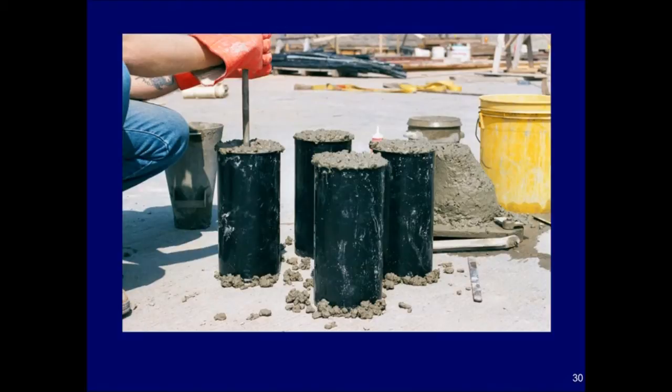Chapter 5 allows a small number of tests to fall below the design strength. The phi factor that the engineer used in the design of the beams partly accounts for the possibility that a lower compressive strength concrete is actually used in the beam. Thus, redesign of the beam using the lower concrete compressive strength is not required.